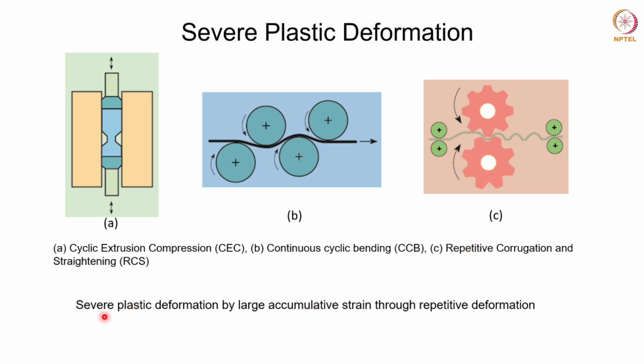All these processes that you see over here in these three figures lead to severe plastic deformation by large accumulative strain through repetitive deformation. So here, as you increase the number of cycles of deformation, the strains accumulate, and that ultimately leads to the severe plastic deformation which the material is supposed to be subjected to for the grain refinement to occur. So this is a repetitive process which is done in a number of cycles.